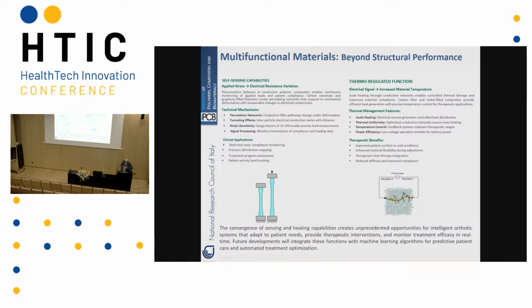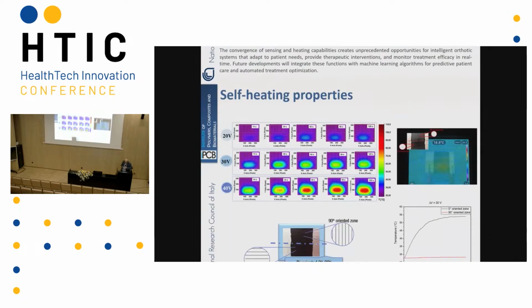Also, you can use it for thermoregulating systems. If you apply a voltage on these materials, just because there is conductivity, but it's not metallic conductivity as I said before, there is a Joule effect. So you have an increase in temperature. Let me show you some examples.